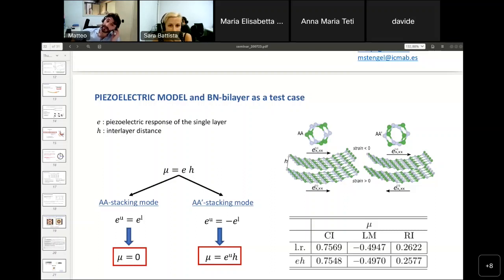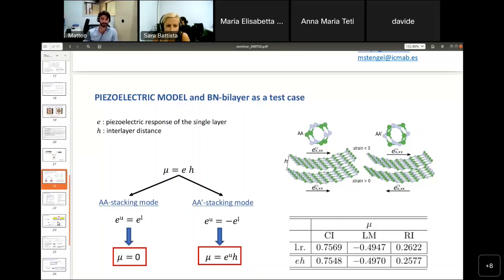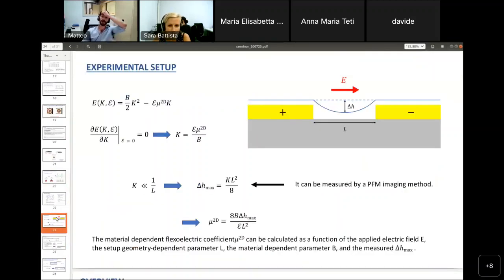Yeah, actually experiments are a problem, in the sense that in the literature you cannot find so many experimental results because of the difficulties in extracting the relevant information in an experiment regarding two-dimensional materials. But recently we also tried to propose an experiment, actually two kinds, but let me first describe this one. We could try to measure the flexoelectric response, in this case the in-plane one, by use of the following experimental setup.